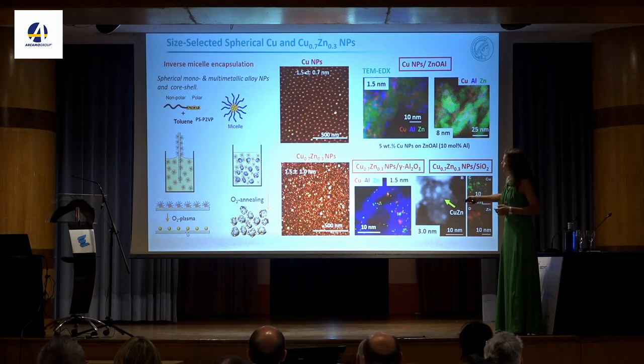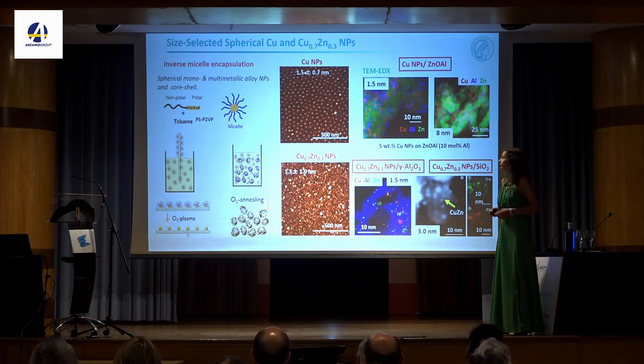Then we can either dip-coat them on a surface and then remove the ligands with an oxygen plasma, or we can impregnate them in the oxide nanocrystalline support, and then we remove the ligands with oxygen plasma in these powders. The nice thing about this method is that you can control the particle size by changing the length of this polymeric head, and you can control the interparticle distance by changing the length of this tail.